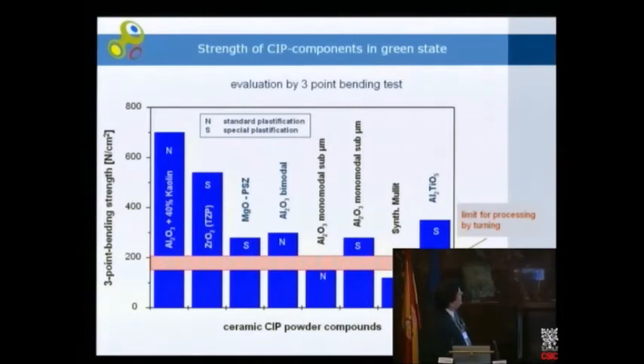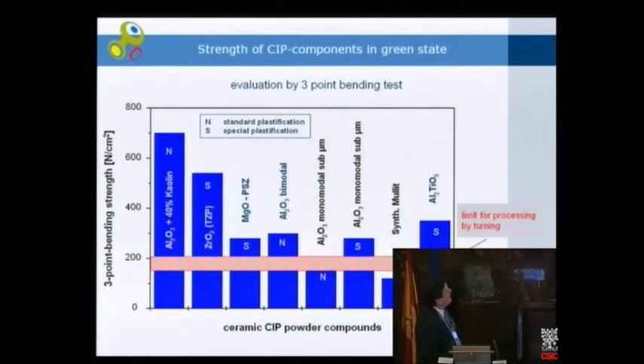And you see, even for submicron ceramics, we can achieve that, but it is not only a question of the powder design, of the grain size distributions, or of the grain design of our component. It strongly depends on the additives. With respect to my former company, I cannot disclose their special know-how, but you see, in one single case, synthetic mullite, we were not able to develop a binder and an additive recipe so that these materials could really be machined to the standards of this company.